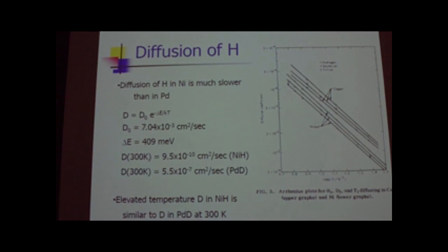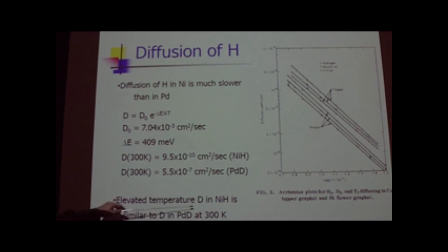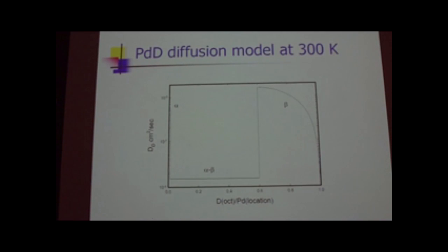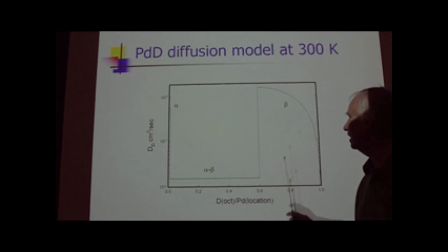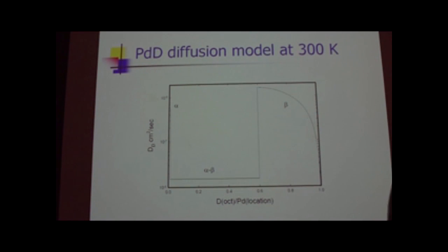H diffuses in nickel, but it doesn't diffuse as well as it does in palladium at the same temperature. But in Piantelli's experiment, the temperature's higher. So nickel does diffuse. And at the elevated temperature of the Piantelli experiment, the diffusion of hydrogen in nickel hydride is very similar to the diffusion of H in palladium deuteride. So in a sense, the hydrogen transport in nickel works the same way as deuterium transport in palladium in the Fleischmann Pons experiment. And we recall the miscibility gap in palladium, but there's no miscibility gap issue in the nickel hydride because there's no miscibility gap present. There's segregation, there's clumps, and there's nothing.